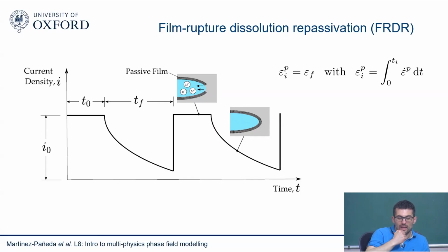And what happens here basically is kind of a cyclic process. So you have your stainless steel, which forms this passivation layer. So let's assume that something disrupts that layer. So your corrosion current density is at a maximum. You have no passive film. You are losing metal significantly. As you start passivating, so as your film starts to deposit, then you reduce the corrosion density. Your corrosion process starts to wind down. But then eventually something happens. You rupture again your passive film, and then you get again exposure, and then again you start repassivating.